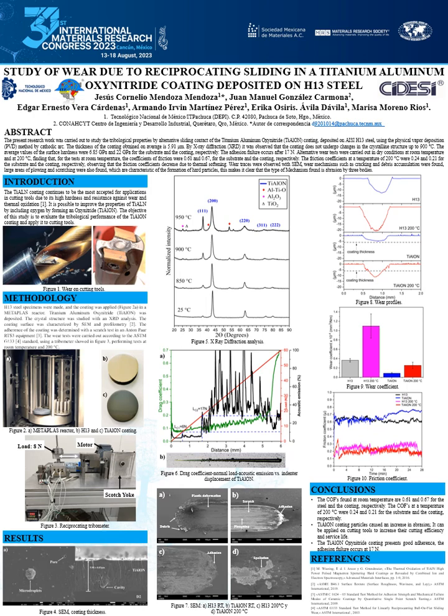Methodology. H13 steel specimens were made and the coating was applied in a magnetron sputtering reactor. Titanium aluminum oxynitride was deposited. The crystal structure was studied with an XRD analysis. The coating surface was characterized by SEM and profilometry. The adherence of the coating was determined with a scratch test in an Anton Paar equipment.